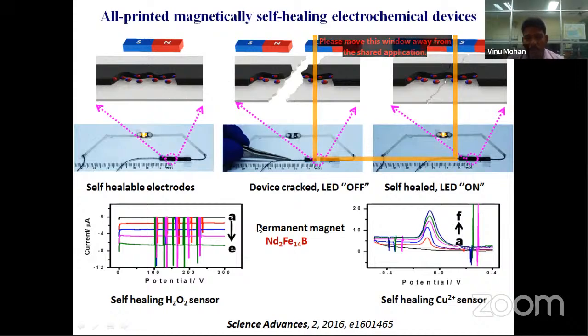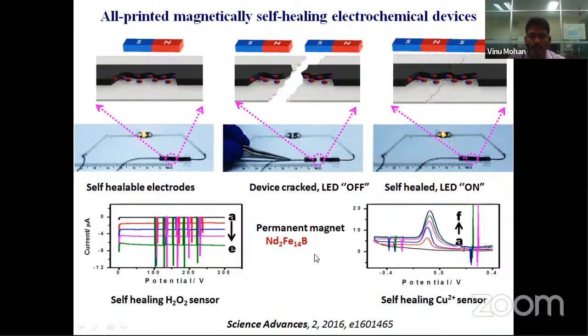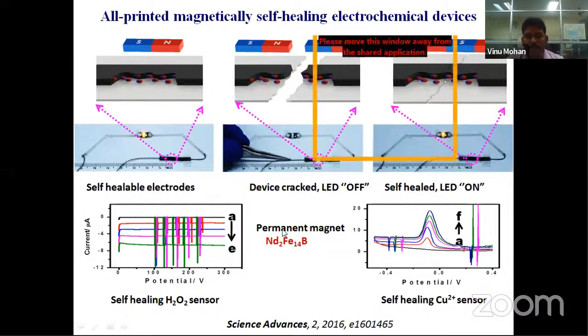So we used permanent magnet particles, which are neodymium iron boron based particles. While preparing the electrochemical sensors or the electrodes, we mix these magnetic particles in also, and when we screen print, we align the polarity of the magnet using another permanent magnet. If we are not aligning, then we cannot have the magnetic property. During the printing itself, we have to align in one direction. Then if you cut the electrode into two, each piece shows the magnetic attraction.